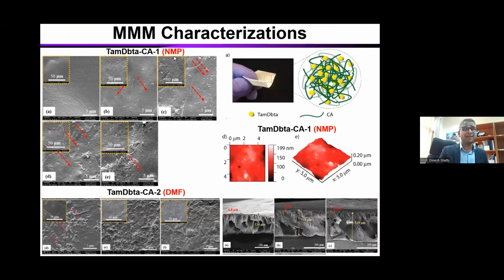What happened when we used NMP as a solvent? The reason is our COF material is an insoluble material, but it has good dispersion in NMP. But it has a relatively okay dispersion in DMF. That you can see in membrane fabrication. When we did fabrication with NMP, you could see a nice distribution of these microparticles of the COF within the membrane, right? But of course, up to what extent? When we went up to 0.8%, it's okay. And also, because of these pillars, they are introducing additional pores within this membrane. But when we go beyond 0.8%, what happened?